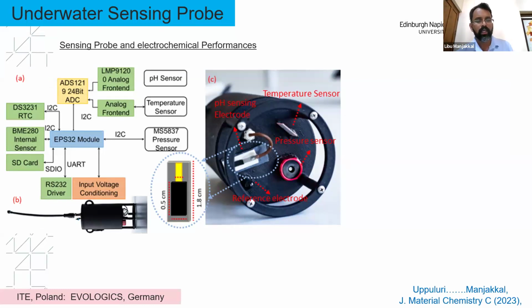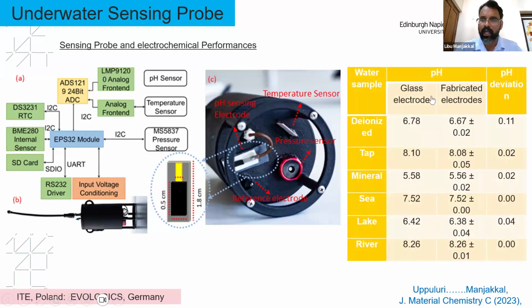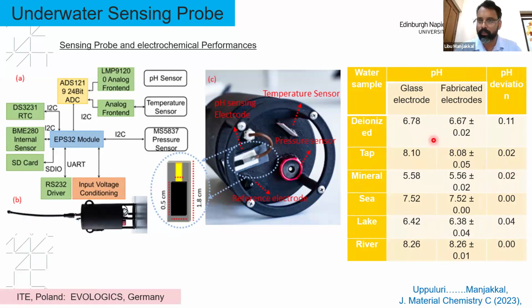For that purpose, glass-based pH sensing again has some issues, for example if you want to integrate with an underwater vehicle or a compact sensing probe. So we integrated our sensitive electrode probe on the underwater sensing probe, as you can see from here, and we monitored different types of water. Comparing the glass-based electrode and our fabricated sensor, you can see that our sensor shows very good performance, comparable with the commercial sensor.